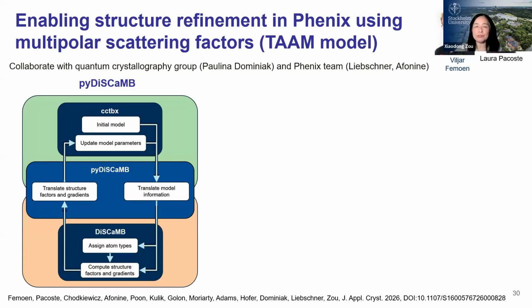Yeah, so we have shown that it's important to use multipolar scattering factors to model the ligand. In cooperation with Paulina Dominiak and also the Phenix team, we have now started to implement the refinement in Phenix. We made this communication. This is the TAAM model, and this is the CCTBX. With this, we can call the scattering factors using the TAAM model, and go back to use this model for the structure refinement of proteins.